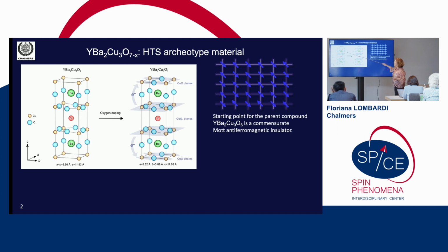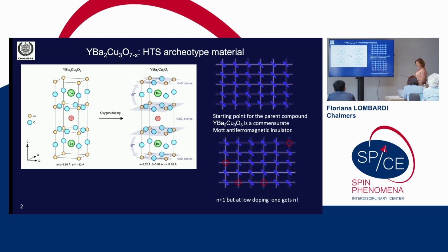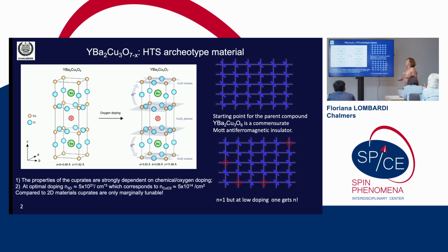So most of the physics happens in this copper oxide plane, and when you have the oxygen, you have transfer of electrons from the copper oxide plane into the chain, and this gives holes and gives conductivity. Why it has been so difficult to progress in this field? It is because in these materials you can change the doping, but you change also the crystal structure. So it is not like 2D materials, where you apply a gate and you can retrieve the phase diagram. Here the carrier density in the plane is very high, so it is really difficult to tune by gating, so they are only marginally tunable.